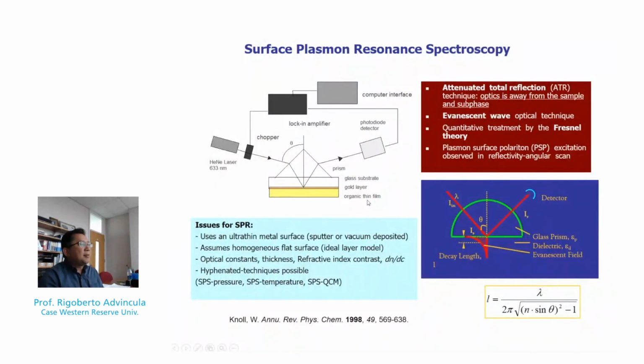Now, schematically, the experimental configuration of an SPR experiment is that you have the incident laser on top of a prism, a gold layer that was coated or attached to the prism using a dielectric media layer, and then you have your organic film, or the film that you want to sense. This sits, let's say, on top of a goniometer, a theta axis goniometer, for example. On the other side, you have the photodiode detector. So the light coming to the prism is interacting with the metal and the dielectric layer. That in turn, depending on the angle as well, is detected as a change in intensity or reflectivity by the photodiode.